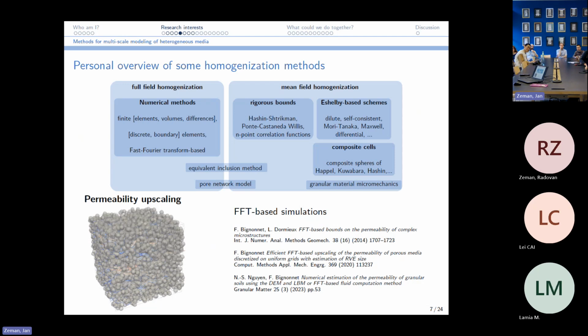So for the numerical part, the idea is you would build some representative volume element. Either you use microtomography of a real sample, or you do some numerical specimen, and then you solve the field equations you have. So for fluid flow, for example, I've adapted these fast Fourier transform-based methods. We generate some sample, we discretize it on a regular grid, which is like a 3D picture with pixels in 3D. And then we solve that problem. The grids can be really big, like I had some computation with 1 billion voxels. So it's difficult for traditional finite elements, I would say.